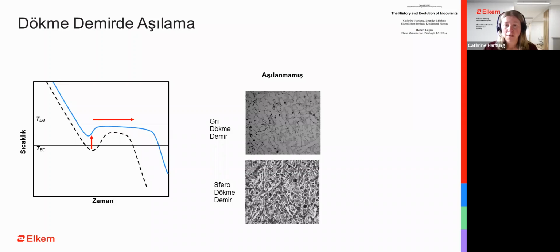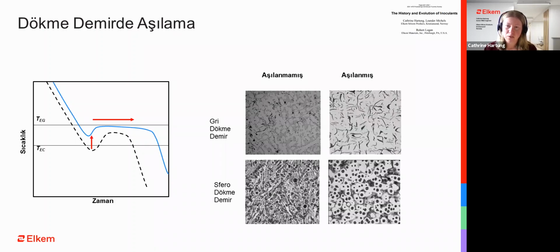And as you can see, before you inoculate, the structure looks either, in gray iron, you have a mixture of undercooled graphite and better looking graphite, while in ductile iron, you predominantly have carbidic structure because your solidification starts below the metastable line, while you get some nodules coming out. But predominantly it is an undesirable structure. So the inoculation then, press next, again transforms the structure from unacceptable to acceptable.